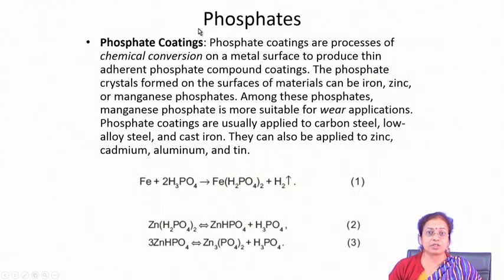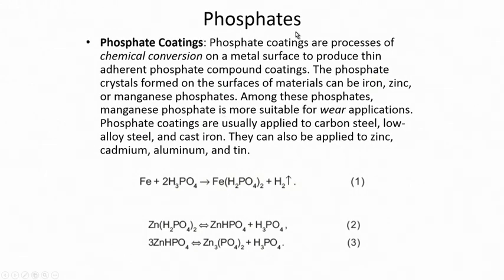The phosphatization process or phosphate coating is not really as hard as oxide coating, and a lot of porosities are also there. So, mostly the phosphatization process is applied as a pre-treatment for subsequent painting operation. This is a very important treatment, and it is also used sometimes to colorize the surface. If you are interested in having a different color on the surface, you do a simple phosphate coating.